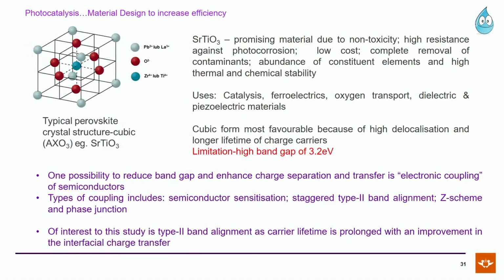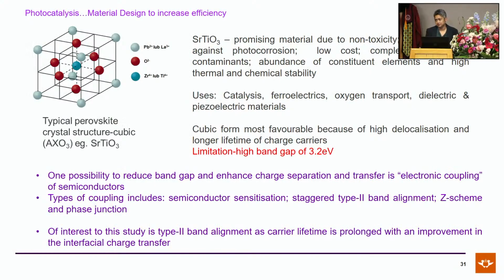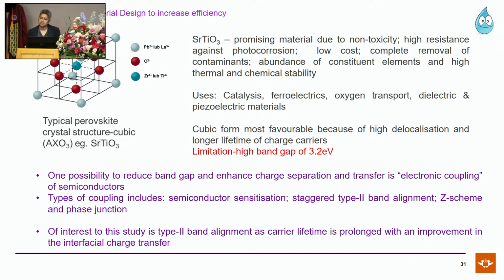In particular, we looked at strontium titanate, SrTiO3. This is a promising material due to it being non-toxic. It has a high resistance against photocorrosion. It's low cost. It helps in the complete removal of contaminants. And it's also abundant; its constituent elements are abundant. And it has high thermal and chemical stability. Where are perovskites used? In catalysis, ferroelectrics, oxygen transport, dielectric, and piezoelectric materials.